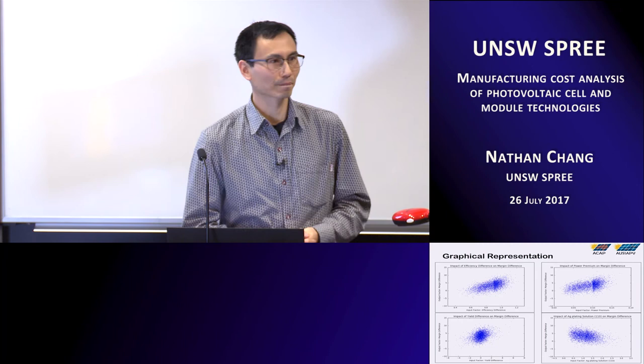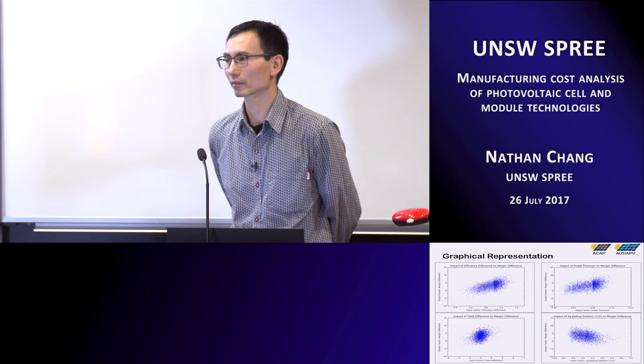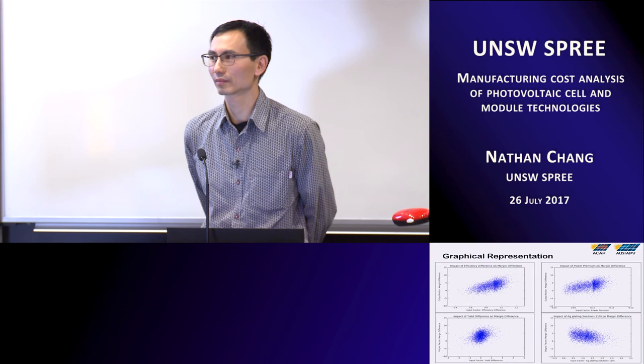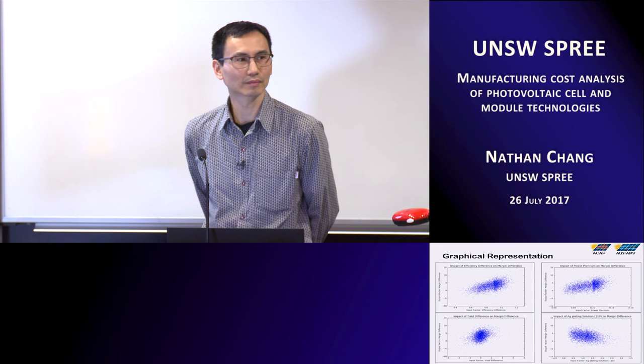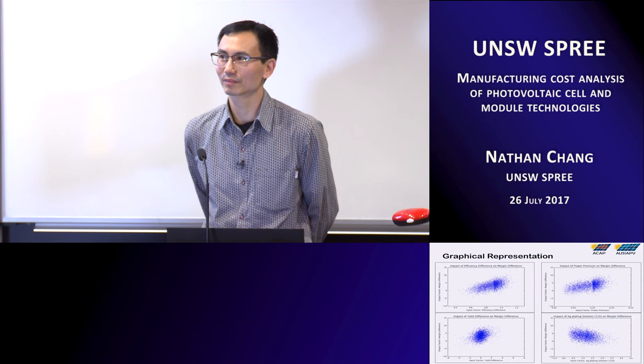Stuart, isn't it the case that the price of screen printed silver has dropped dramatically in the last 5 years? I suppose it depends on how much silver you use. The cost of silver went up and then it's come back down. But also they've changed the formulation, so you've got way less silver in the actual paste. Yeah, they're using a lot less paste per cell. I think that's a big factor. So I think Nathan's worked with current numbers that have all of those improvements in them, which have narrowed that split between the plated and the screen printed technologies. I guess the difference might be that you'd probably redesign the cell if you were using copper plating. You wouldn't have five bus bars. You'd go back to having three or something and save costs there.